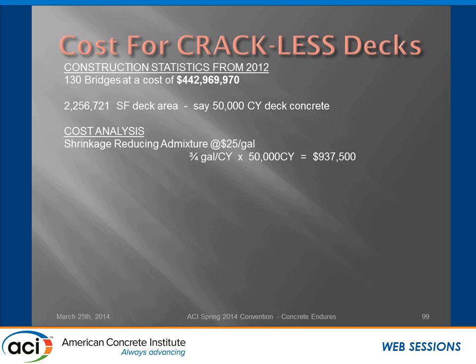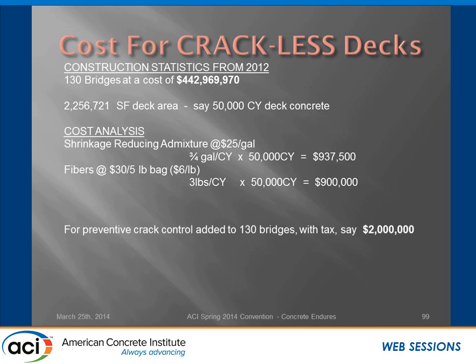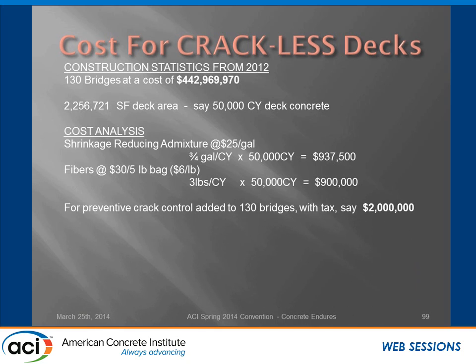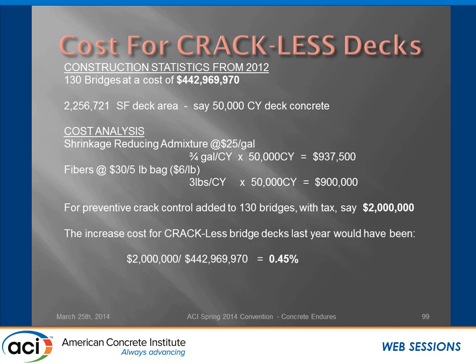By adding 3/4 gallon of shrinkage reducing admixture to all those bridges, if we would have done it, it would have cost us less than $1 million. And similarly with 3 pounds of macro fibers, again, less than $1 million. So we could have had 130 bridges built in 2012 for less than $2 million. That's pretty small change. As a matter of fact, if you divide it into the construction cost, it's less than a 0.5% increase if we would have done all the bridges.